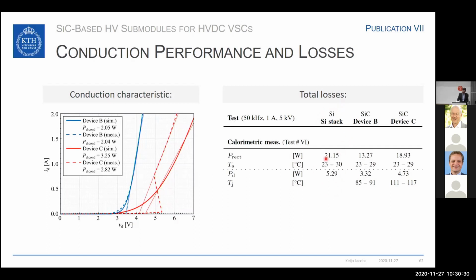We measured losses of 21 watts in this case. And for the conduction optimized device, we measured 13 watts. And the difference between these two is 37%. So we get a reduction of the losses of 37%. Since device B is a 10 kilovolt device and the silicon stack is only an 8 kilovolt device, if we interpolate linearly, we would get a loss reduction of around 50%, so half. Another interesting point here is that only 19% of the losses are reverse recovery losses. So the optimization of this device for the circuit operating at 50 kilohertz is quite good.